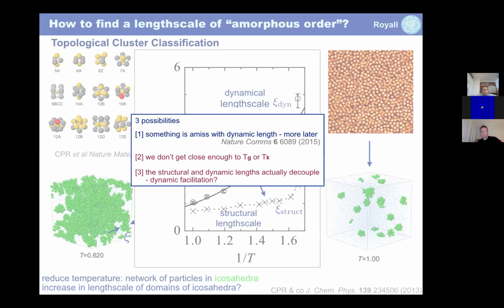So it may be that there are other structures that we don't detect. That's possible. It may be that we're missing the dynamic length, so we're measuring that in a bad way, which is possible, and we looked at it, but I won't talk about that now. It's also possible that we don't get close enough to the real glass transition. I said the change in relaxation time was a factor of 10,000 here, but actually it's 14 decades of change in relaxation time to get to TG, where thermodynamically nothing happens, and it's very hard to get past TG.